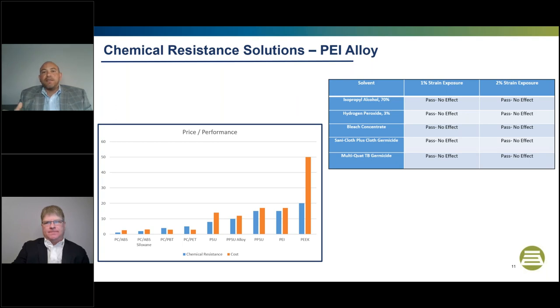Crystalline materials are typically going to give you really great flammability properties and chemical resistance. But the amorphous materials like PC and ABS, they're going to give you the ability to mold very accurately. So when you're molding a large part, it gives you dimensional stability. So we have a ton of solutions, PC-PET, PC-PBT. What's really great and interesting on the amorphous side is PSU or UDEL and PPSU, RADEL, and even ULTEM, polyetherimide. They're all transparent. And so they're easily colorable. They have really good inherent flame resistance properties, and they have great chemical resistance. The price is just significantly higher.